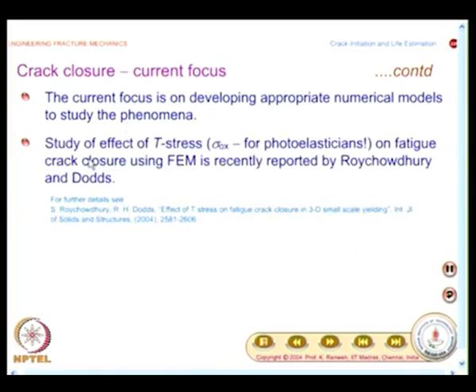Not only this, they also want to find out the effect of T stress, that is sigma naught x, for photoelasticians. We have spent ample time in understanding this when we discussed crack tip stress and displacement fields. So, they do not want to restrict only to the stress intensity factor K, they also want to go to the second term, and such an attempt is made using finite element methods, which is recently reported by Roy Choudhury and Dodds. This is a paper in 2004.